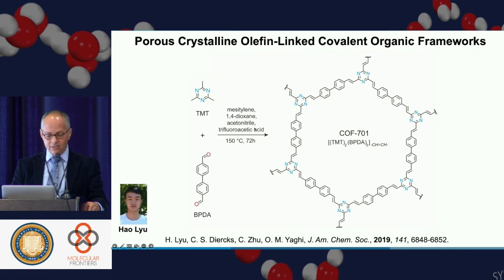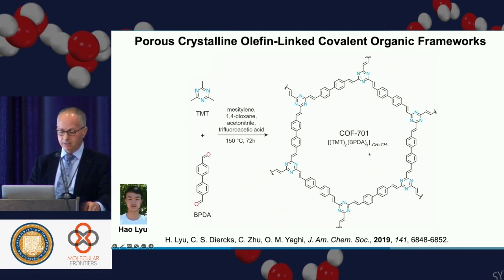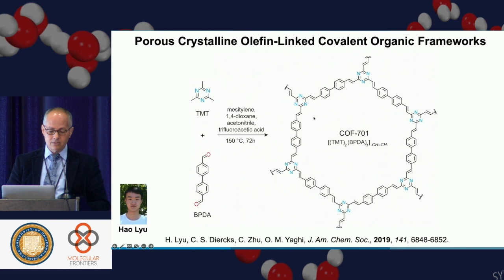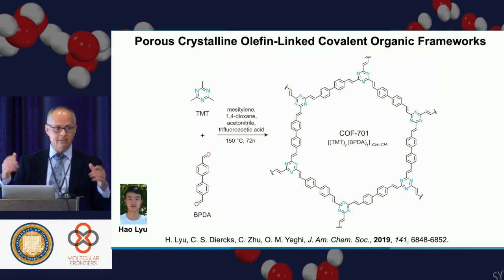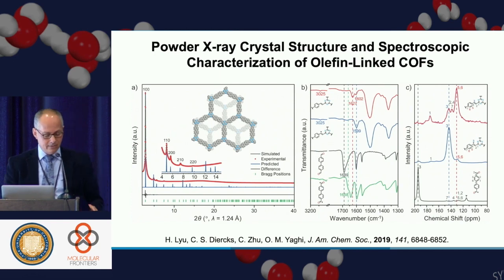So these are the conditions under which you make these olefinic linkages reversible, and therefore you crystallize this material. Why do we want olefins? Because we want backbones that are extremely stable so that we can use them for water harvesting or carbon capture, and they can stay in a power plant for many years before you have to replenish the material. You need those strong bonds so that they don't hydrolyze, they don't decompose under those harsh chemical conditions.